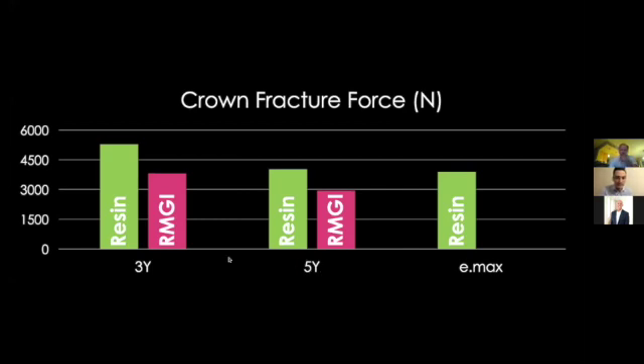And then with the 3Y zirconia, if you conventionally cement 3Y zirconia at this thickness, it was the same strength as these other materials bonded. And then, this is a little controversial, but in our study, we showed that if you bonded 3Y, you could strengthen the material even further. So if I've got a really thin molar crown, one of those where I get it back from the lab and I've got the model there and I'm looking, and it's like, oh my God, I feel so bad. What have I done to this poor lab? And they've been so nice to somehow get a restoration to fit inside of there. But man, it's thin. So I'm like, okay, I'm bonding this guy. Even if I didn't need it for the retention, I would bond it to reinforce the material for its strength.